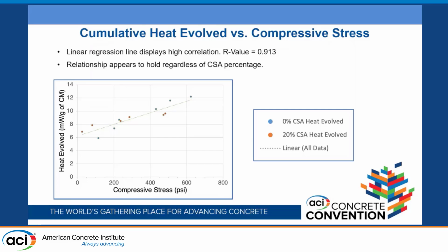percentage of CSA is changing, because we looked at both 0% CSA and 20% CSA. So in this specific graph, you'll see that this linear regression line actually goes through all the data. So it means that despite the fact that there may be varying levels of CSA, it's still valid as a predictor of the actual mechanical properties of the concrete at early age. By that I mean the heat evolved as a predictor.